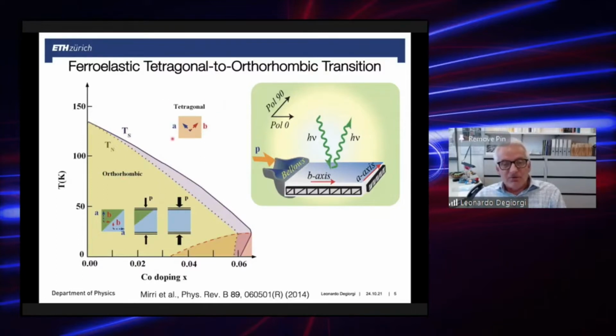So when you apply uniaxial stress in the nominal tetragonal regime, you can exploit uniaxial stress as an external symmetry breaking field, which allows you to stress-induce some orthorhombicity. Now, we developed a mechanical stress device, which consists of a bellows, and by flushing helium gas in and evacuating the same, we can exert or release stress on the specimens, which were cut and oriented in such a way that upon applying stress, the domains preferentially align along the shorter orthorhombic b-axis, so parallel to the direction where stress is applied. And this allows us to perform optical experiments as a function of polarization of light along both stress-induced orthorhombic axes.